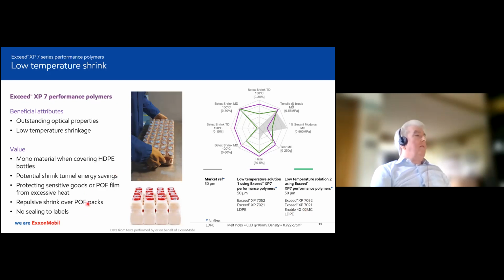Okay, now the other advantage, of course, with things like probiotic drinks, which are often wrapped in POF film, is that this sort of film almost has a repulsive shrink effect on it. So in other words, it can be used to go around these packs of probiotic drinks, and they're fairly easily released, and you're not getting the sealing issue that you would have to some of the labels.